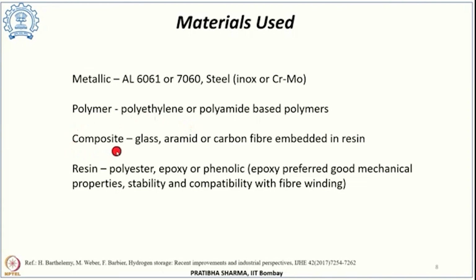The composite which will be used, the fiber that could be used: in earlier pressurized vessels glass was used, and then it was replaced. However, glass is still more economical, but when it comes to higher pressure operations, 35 MPa or 70 MPa, then carbon fiber is used. So the options could be either glass, aramid or carbon fibers, and these could be embedded in the resin. And then there are choices for resins also. These could be polyester, epoxy or phenolic. However, the more preferred one is epoxy resin, and the reason is they have very good mechanical properties, they are stable and they have compatibility with the fiber winding. So the fiber resin composite, which could be a carbon fiber and epoxy resin, is used in type 4 cylinders.